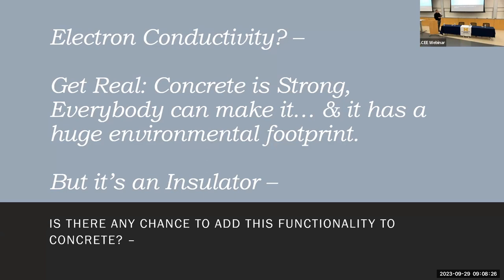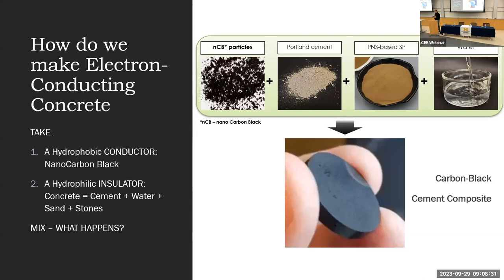So how can we add this function to the material? Well, we need another component. The component which we're using is nanocarbon black, which is a relatively cheap material. We'll come back to how it is produced. We mix it up with Portland cement, put some superplasticizer in there, water, and then we obtain carbon black cement composites. Now, what is really fascinating about this material is the magic of chemistry.